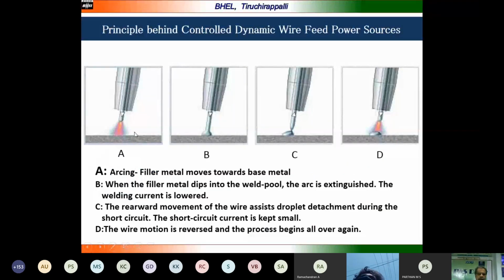Here you can see how the process is working. In A is the arcing, where the arc occurs and the filler metal moves towards the base metal. Then the filler metal dips into the weld pool, as shown here in B, and the arc is extinguished. The welding current is lowered, because of that the current is coming down, and actually the heat input is going down.